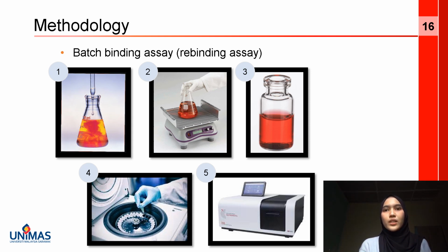For the UV-visible spectrophotometer, the lambda maximum of standard MR at 520 nanometer will be used. Thus, the absorbance of the extracted sample will be measured at lambda maximum. The extraction efficiency of the sample will be calculated using the extraction efficiency formula.